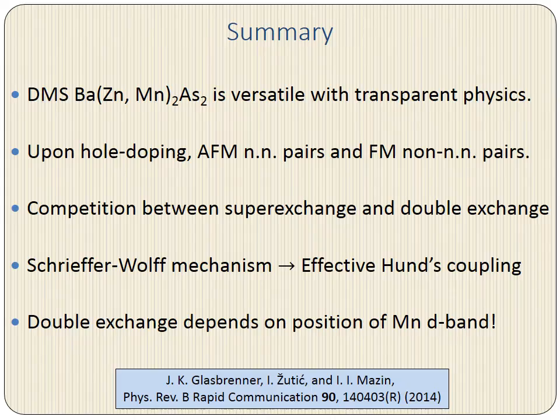In summary, I talked about a new and exciting dilute magnetic semiconductor, barium zinc arsenic doped with manganese. This material is versatile, and we saw that it has transparent physics. We saw that if we hole dope the material by replacing the bariums with potassium, nearest neighbor manganese pairs will have an antiferromagnetic coupling, but non-nearest manganese pairs will have a ferromagnetic coupling. The magnetic interaction in the system we saw is a competition between superexchange and double exchange. The double exchange is due to the Schrieffer-Wolff mechanism, which gives rise to an effective Hund's coupling. And this effective Hund's coupling is exciting because it means that our double exchange interaction depends on the position of the manganese 3D band. And that means that the Curie temperature in principle may be tunable.